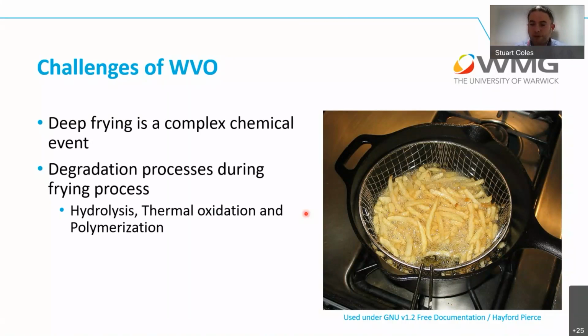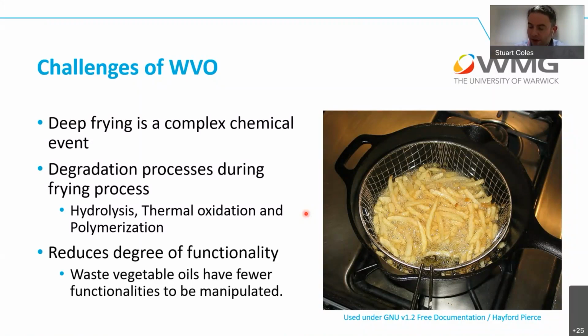You've got degradation processes that are happening to the oil, so things like hydrolysis, because there's still water in there, and particularly the food that when you drop in there adds water to the system. You've got thermal oxidation of the triglyceride. You've got potential polymerization of some of the chains to make oligomers and dimers, trimers, etc. All of this effectively reduces the degree of functionality that you have within that oil. So we started off with the oil having a nice versatile feedstock, but we know that through the cooking process we were going to start to reduce that level of functionality.